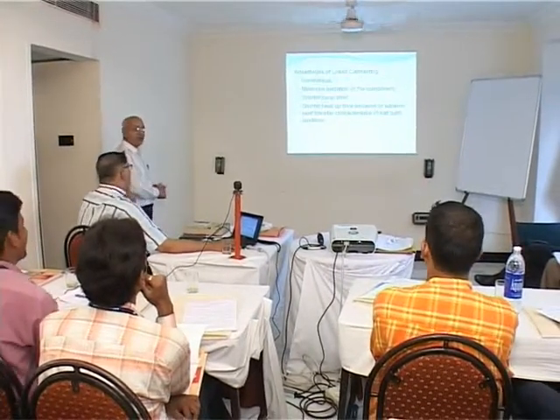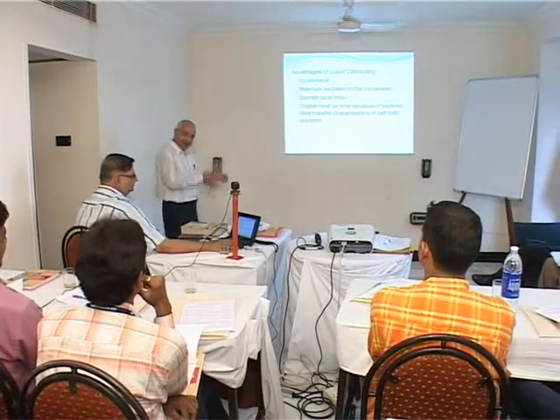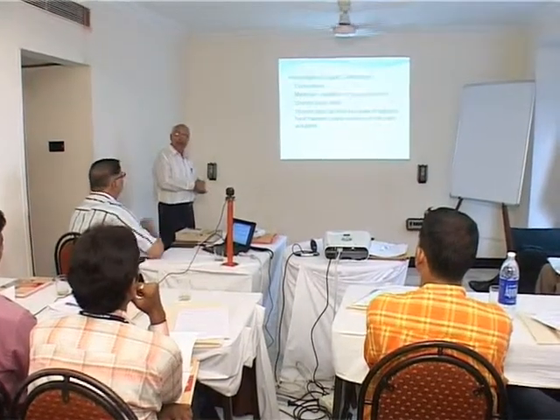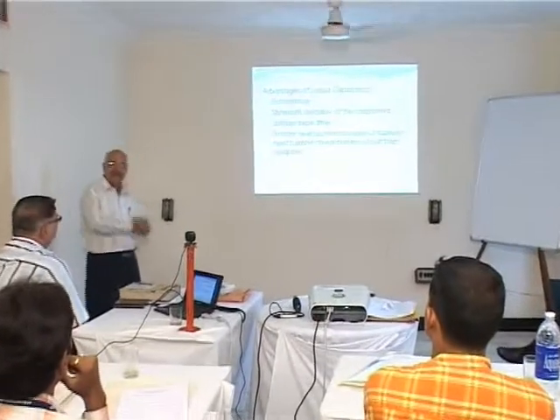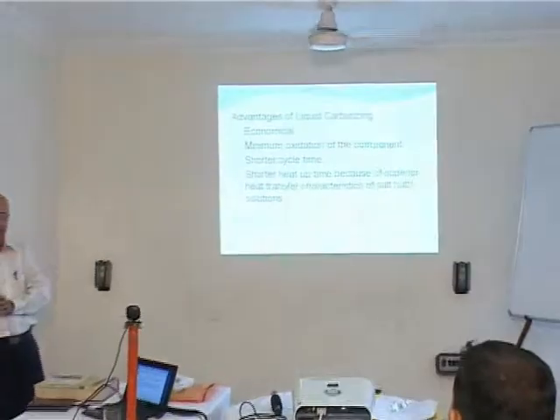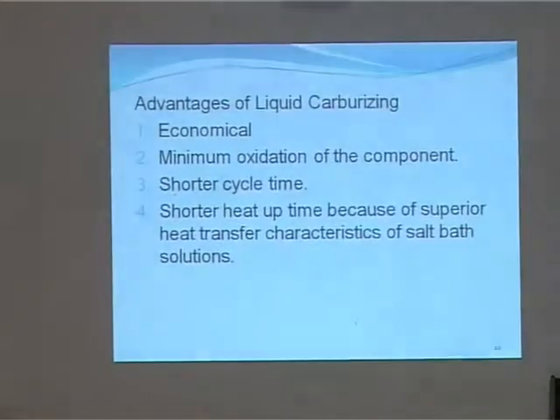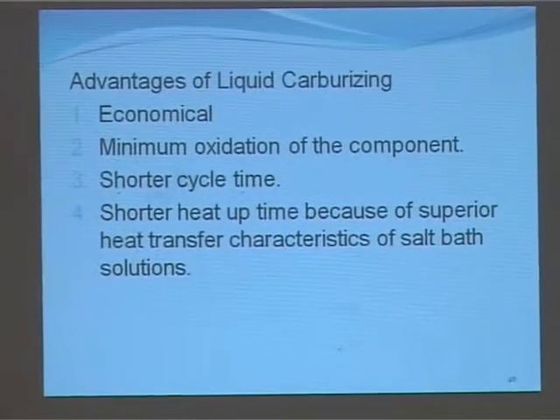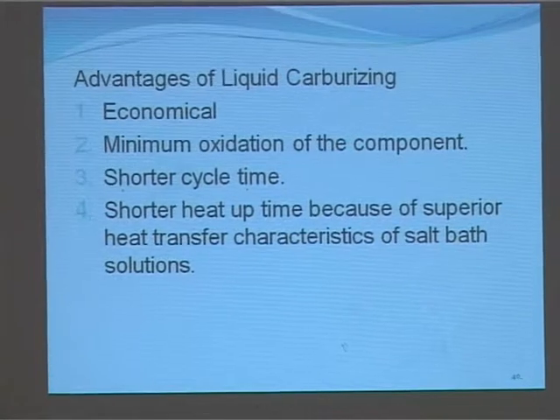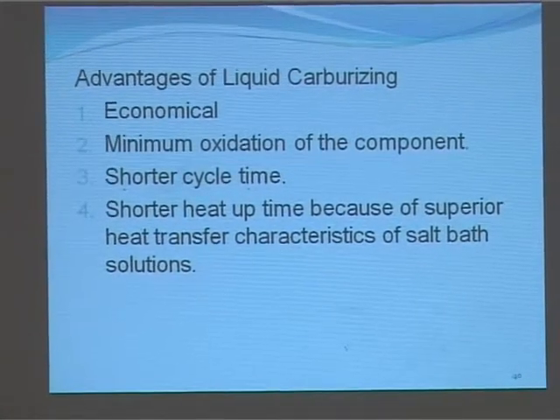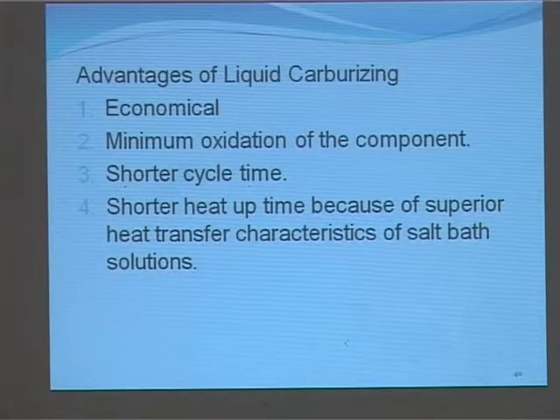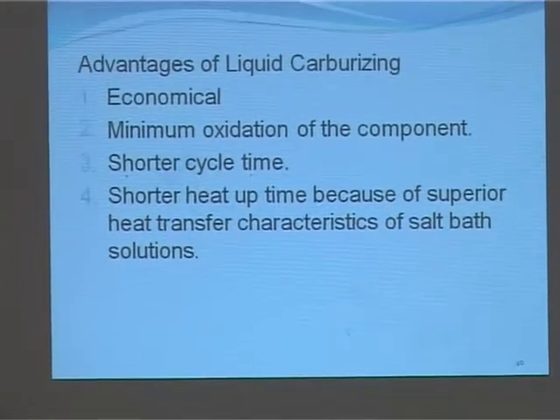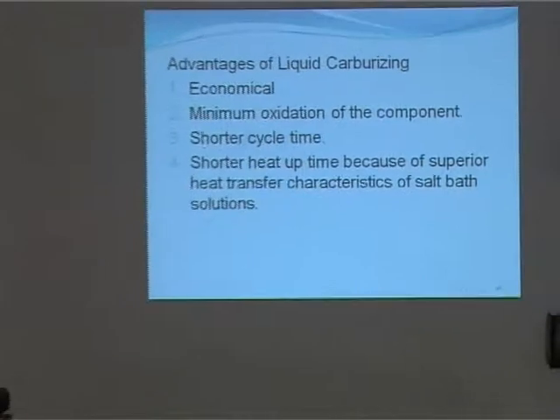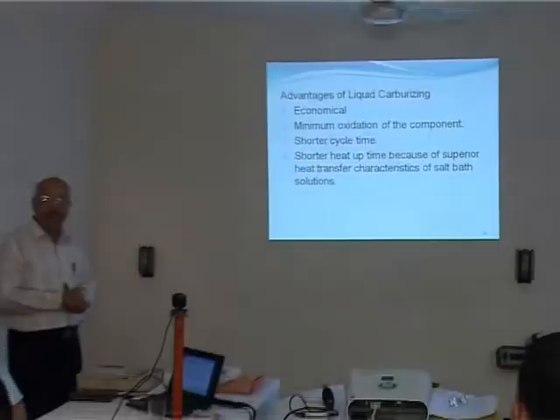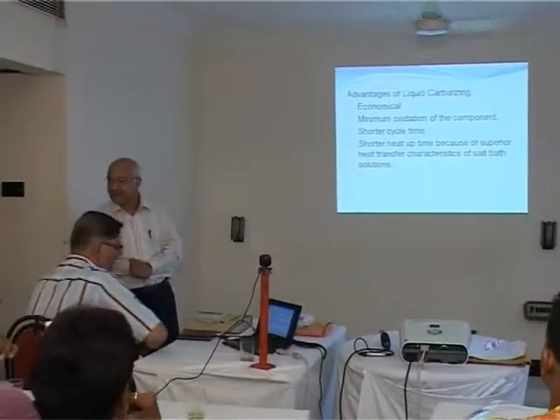Minimum oxidation of the component. The component is dipped into the liquid. The only time it can come in contact with oxygen is when you are quenching. But at that time also some layer of liquid is there. So whenever you are doing liquid hardening or carburizing, oxidation is not there. What is oxidation? Whatever air is available in the environment or in the furnace, it reacts with carbon. And if decarburization is taking place, your hardness will go down. If your hardness is going down, just check whether decarb is taking place. But in a salt bath, that risk is not there.